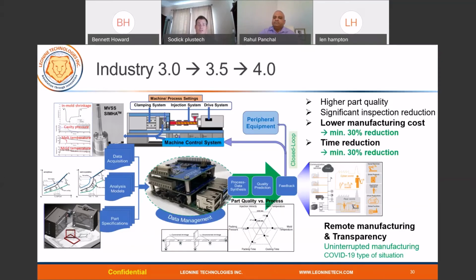Great. A question here regarding transverse versus axial shrinkage. Does the sensor account for this? And what about parts that don't adhere to normal design considerations, such as thin walls over a long run? Generally, we found that the sensor is very accurate for thin walls, so the dimension prediction capability of the sensor will be very high. Measuring the shrinkage at the thickness is the most accurate, because a lot of people talk about transverse shrinkage at the length or the width. But if you measure the shrinkage on the thickness, that will give you very accurate shrinkage and dimension prediction capability compared to thinking about the length.